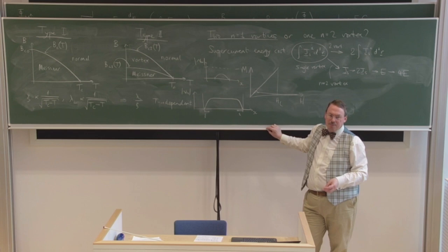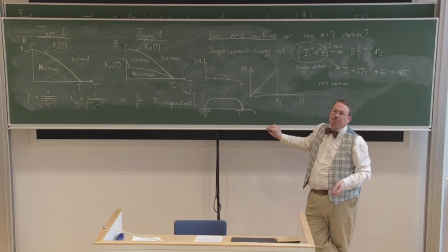I think these layered compounds are quite informative there, because as you make them layered, right, and you pull the layers apart, you've got to be aware that the coherence length is very anisotropic. Right, so I think you were worrying about the depth dependence relative to the coherence length, but the coherence length shrinks in the C direction as you reduce the coupling.